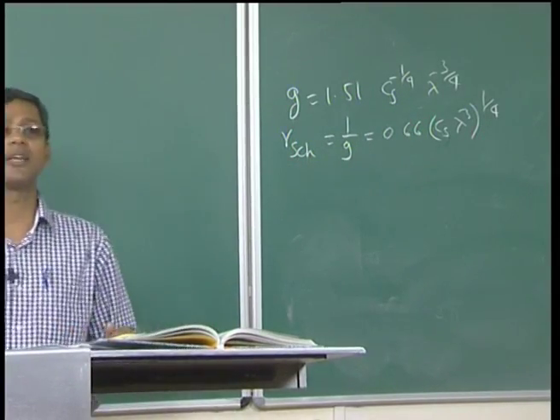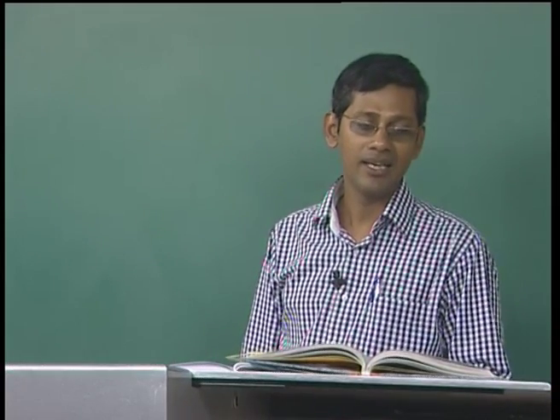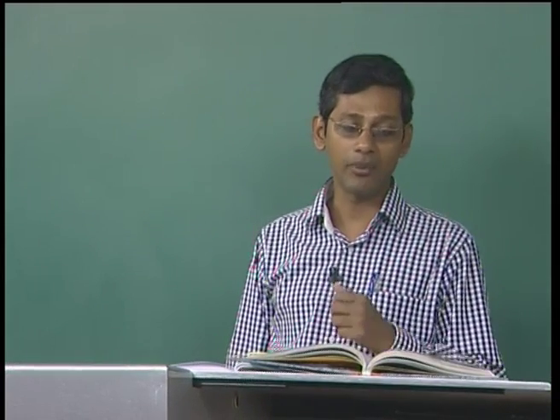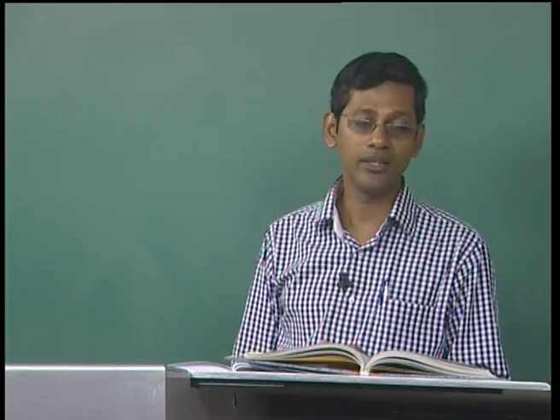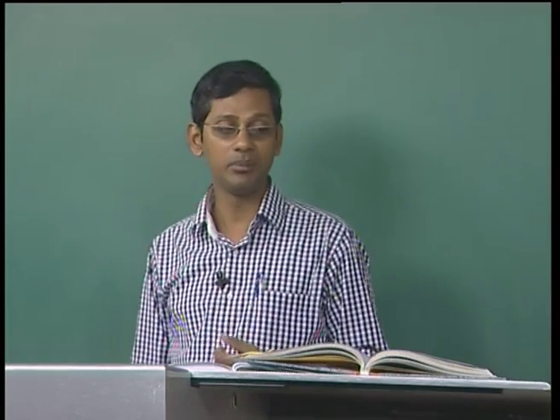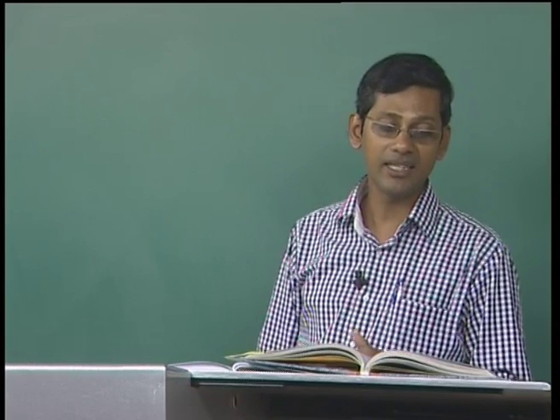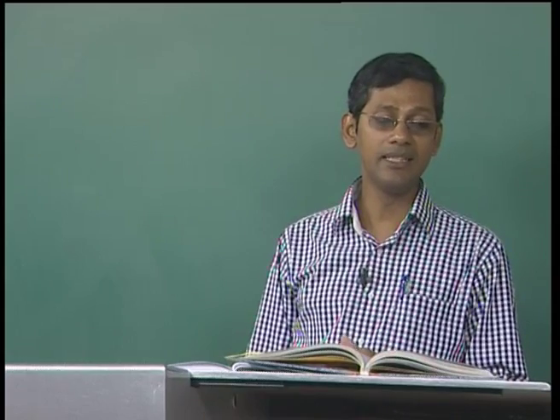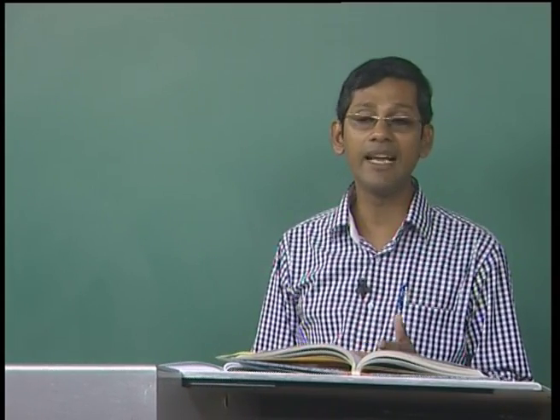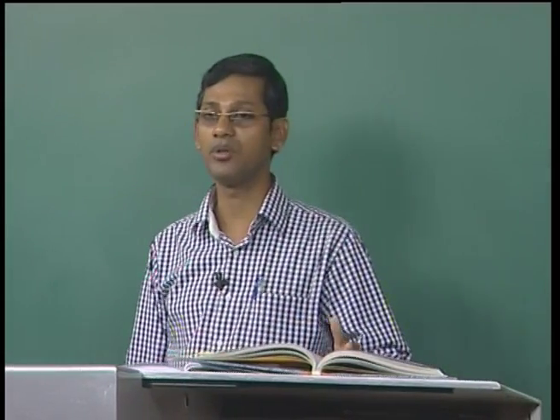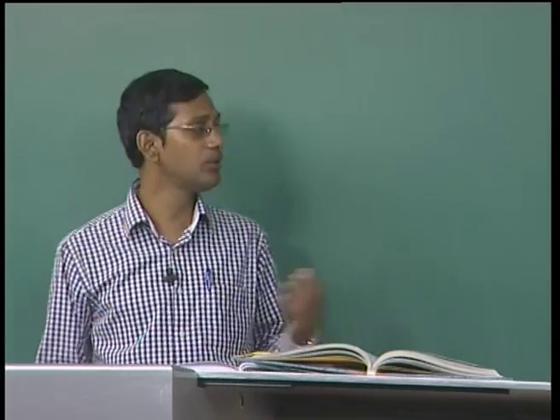In fact, there are reports that in the 1970s, a detail of 0.66 Angstrom was actually achieved, when the interpreted resolution was about 3.3 Angstrom. So, you can see that having details in the image does not mean that you can gain any useful information about the microstructure. So, there is a distinct difference between the resolution limit and the information limit as far as the microscope is concerned.